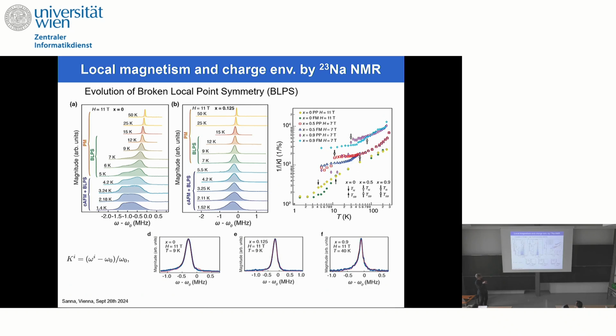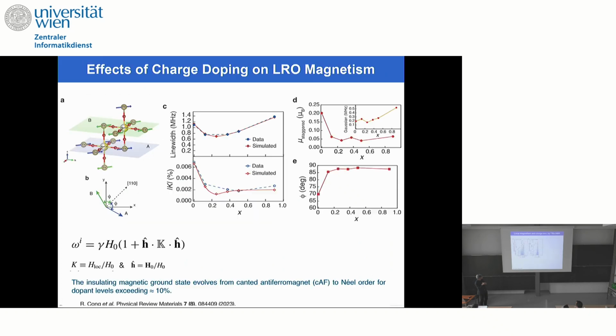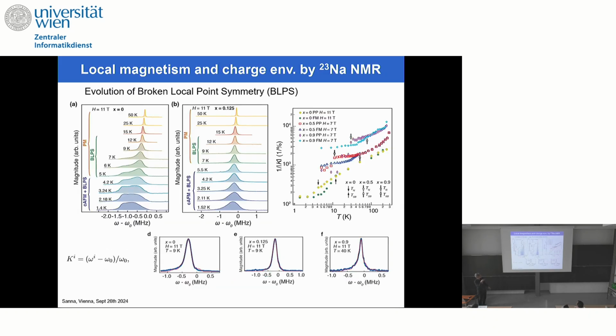Now, we have something more. In the intermediate phase, before the magnetic state occurs, we have a slight change in the shape of the NMR signal, which is not anymore perfectly symmetric, but is distorted. The fact that it is distorted is very easily seen if you plot the position of the peak and the position of the first moment of the peak. If the peak is symmetric, the first moment of the distribution and the position of the peak coincide. If it is distorted, then they are split.